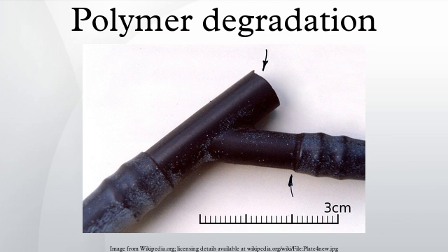Polymers affected include bismaleimides, condensation polyimides, triazines, and blends thereof. Degradation occurs in the form of dissolved resin and loose fibers. The hydroxyl ions generated at the graphite cathode attack the OCN bond in the polyimide structure. Standard corrosion protection procedures were not found to prevent polymer degradation under most conditions.